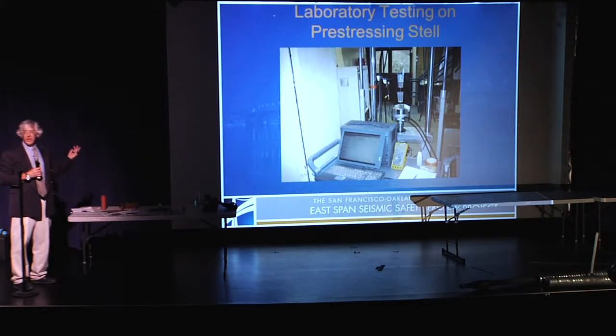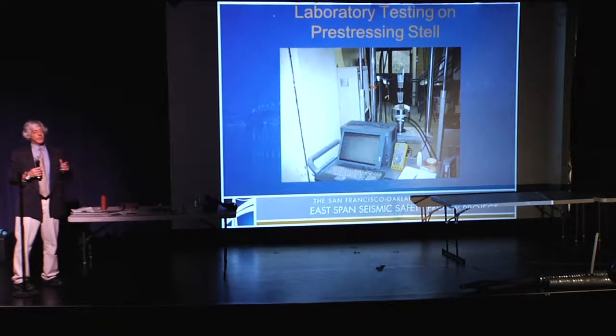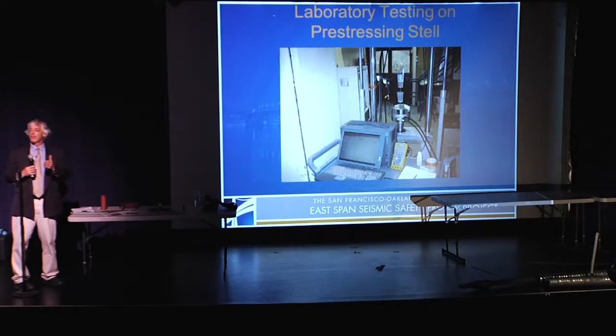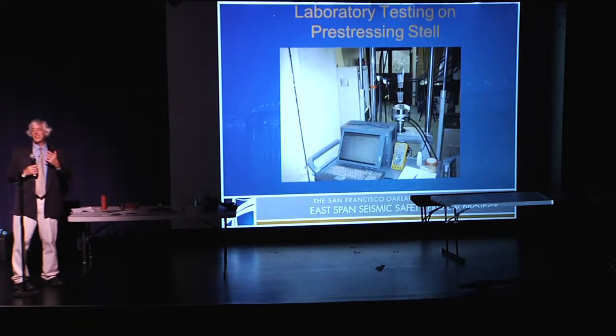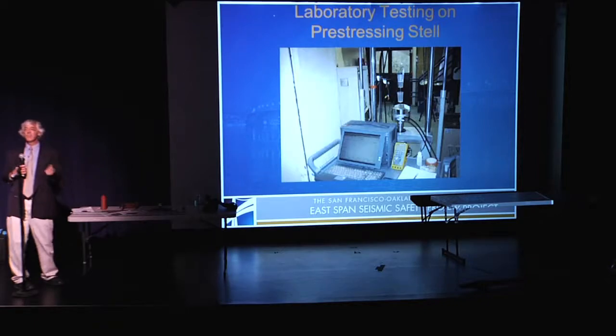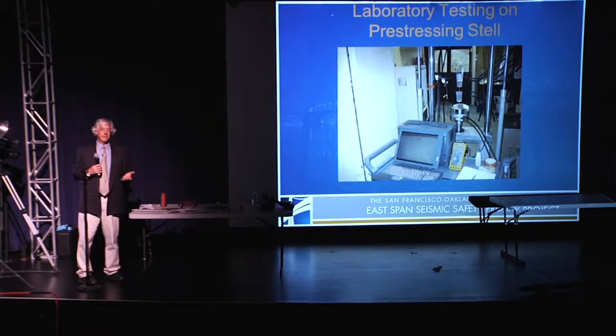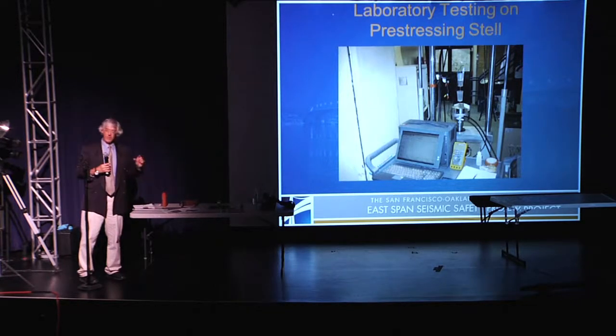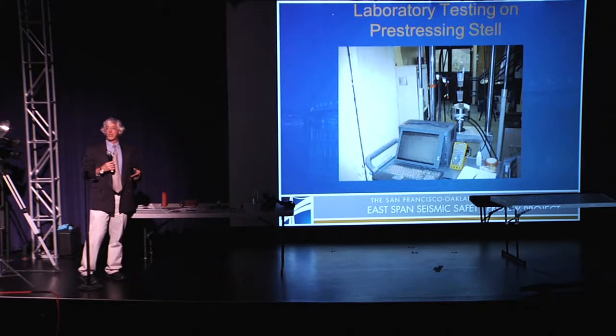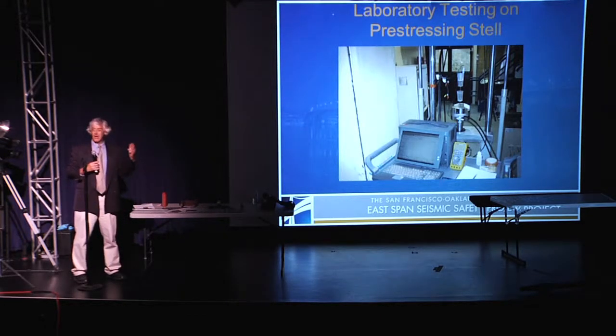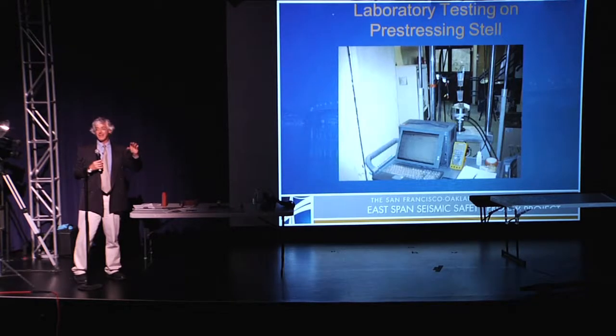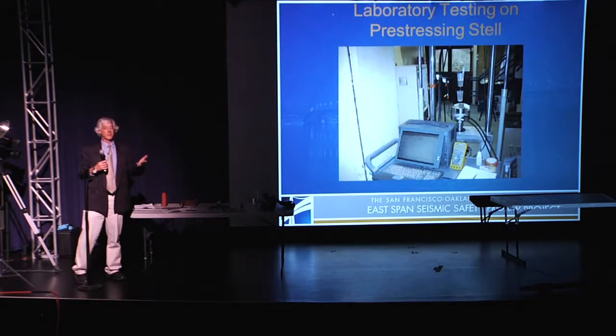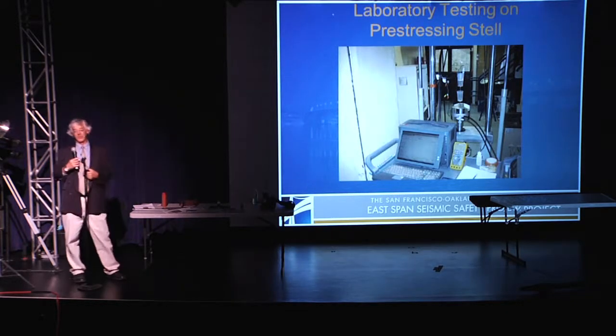And a few of them we actually took out, but others we actually go through an evaluation process of, do we want to take it out? And some we did, and others we go, well, you know what? When we take it out, we actually do some other damage. What's the right balance? And we went through an evaluation of how much extra do we have? And we reviewed our calculations, and we had about 10% extra pre-stressing, right? So we got like 10% extra, and that's on top of code factors of safety and capacity reduction factors. However, we did have about 1.5% that we lost something like 5% of their capacity in. But if you think about 1.5% times 5%, that's less than like 0.1%, or a small fraction of 1%, as compared to the 10% extra we have in reserve.